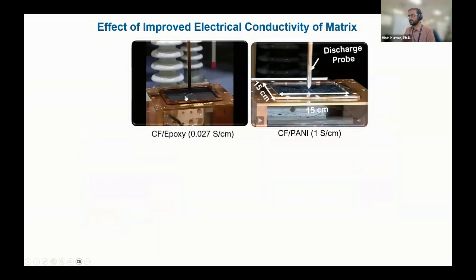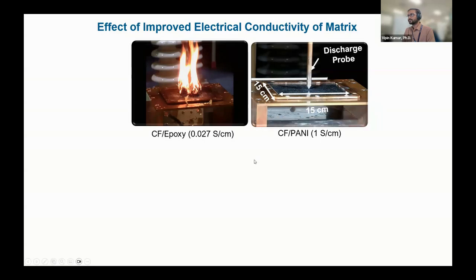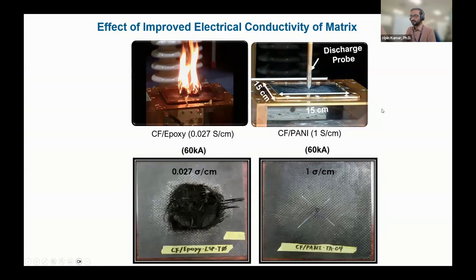So as I mentioned, now this is a one-on-one comparison. A CF epoxy with no conductivity, and a polyaniline-based resin system with higher electrical conductivity. And then you see a very good dissipation of the electrical current from the surface without seeing the damage. So this is the difference between non-conductive composites and conductive composites against a lightning strike.